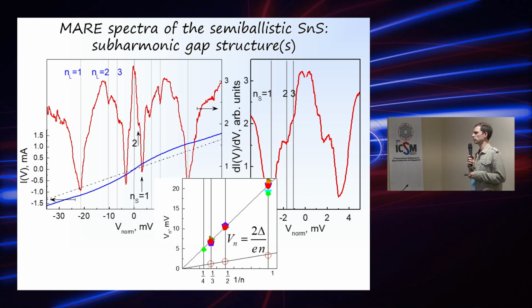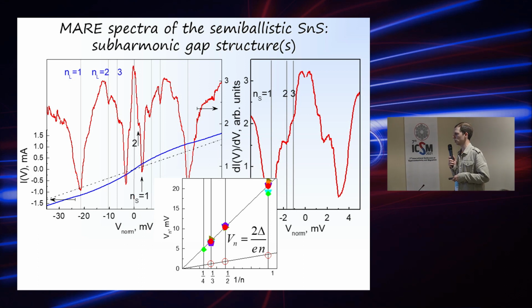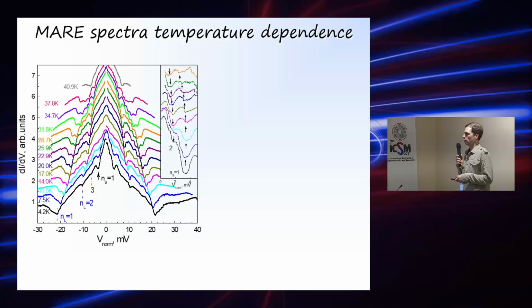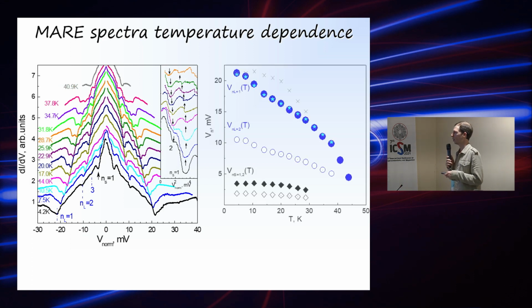But the problem is that it was the only contact where we could detect something near zero bias, but we could expect that there is also some input from the small gap in this compound. But it's hard to say the same for other contacts. And here we take these spectra with temperature, and this inset shows the position of the subharmonic gap structure for the small gap, and here is the result of this position.